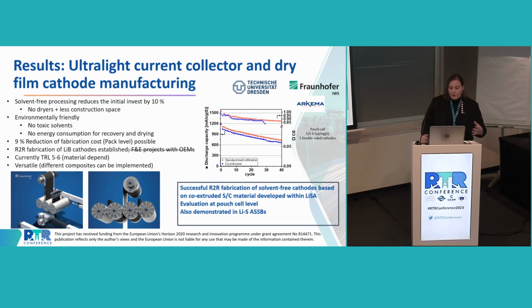Then moving on to the project, in order to make this safer production battery, the Fraunhofer Institute in Dresden proved that with this new solvent-free process, they were able to obtain these sulfur-carbon composites to build the electrode. So no dryers are needed for that process, no toxic solvents are needed, actually no solvents at all. So it's all a solid process, so you reduce the fabrication cost by up to 10%.